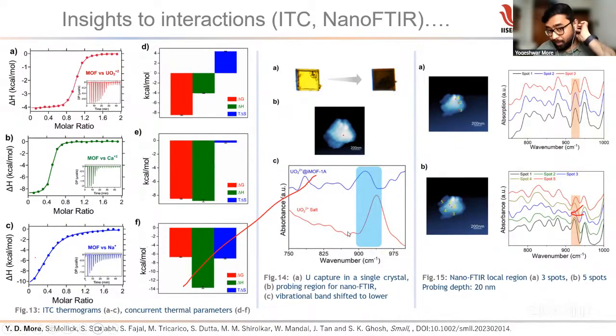So this we did at Oxford. While doing so, what we observed, we did in a 200 nanometer size MOF crystal, and we did at several places. So here you can see these two bands are concerned to the uranium and the MOF interaction, and hence we understood, and we have done the repetitive measurement. You can see spot 1, 2, 3, similarly spot 1, 2, 3, 4, 5, all over the crystal and different crystals. So this was a bulk crystal which was exposed to the uranium, and then it was dispersed in the water, sonicated, made to the finest size of 200 nanometer, and then we did all the nanospectroscopy.